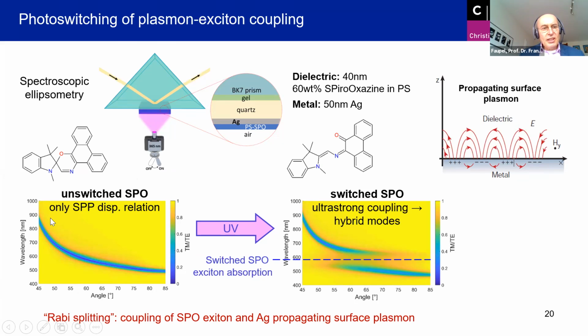And what you see here is the dispersion relation of these propagating surface plasmons for silver, which was recorded by spectroscopic ellipsometry. And now you see if we incorporate these chromophores into a polystyrene film, which we put on top of the silver, then we get this coupling between the surface plasmons and these chromophores. And due to this exciton plasmon coupling, if the frequency matches, then we get a splitting like the two spring pendula, which upon strong coupling split into different resonance frequencies.